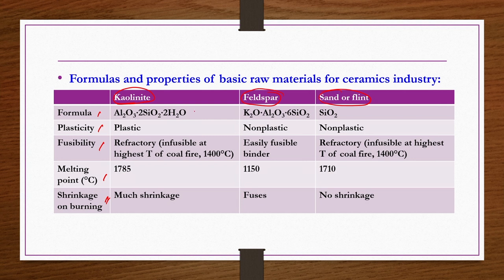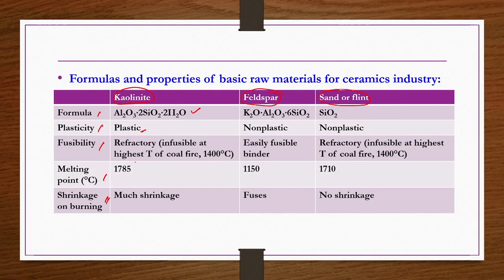So kaolinite formula, we already know, is Al2O3, 2SiO2, 2H2O. It is plastic in nature. So it's a good one, because most of the raw materials of the ceramic industry should be plastic. And then fusibility: they are of a refractory nature because they are not fusible even at a temperature of 1400 degrees centigrade. Why are they not fusible even at this temperature? Because their melting point is 1785 degrees centigrade, right? But the problem is that on burning, they undergo much shrinkage.